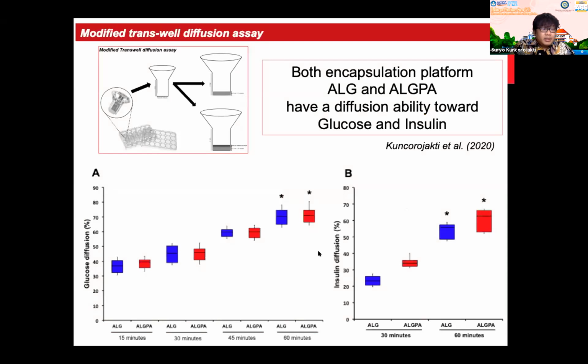Then we're going to move to the diffusion study. To evaluate the diffusion ability of the alginate and alginate-pluronic encapsulation platforms, we use the modified Transwell diffusion assay here. This figure shows the glucose and also the insulin diffusion in both encapsulation platforms after 60-minute incubation. The result of this study shows that both encapsulation platforms, the alginate and also the alginate-pluronic, have diffusion ability against glucose and also insulin.